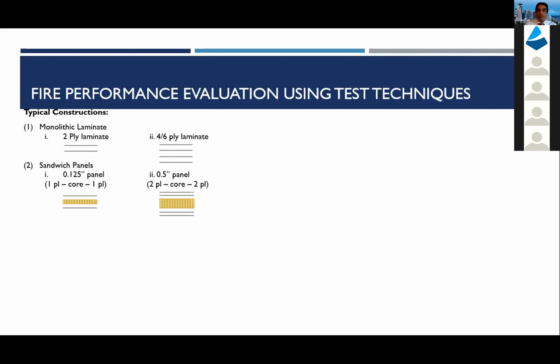Before starting any test, it is important to make sure what type of sample construction is to be used for the test, in order to get more accurate information from the test. The typical constructions used for this type of test are monolithic laminate construction and sandwich panel construction. In monolithic laminate constructions, mainly 2-ply laminate and 4 to 6 ply laminates are used for the test,